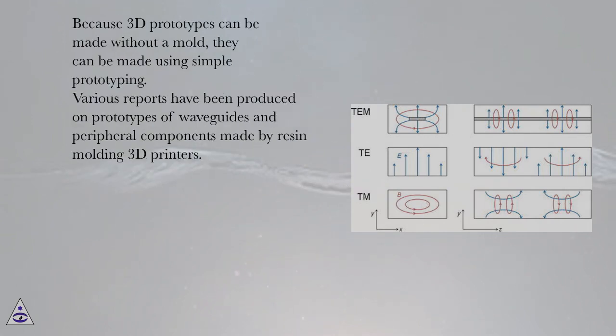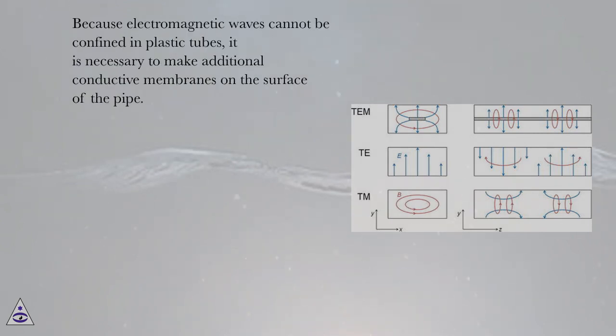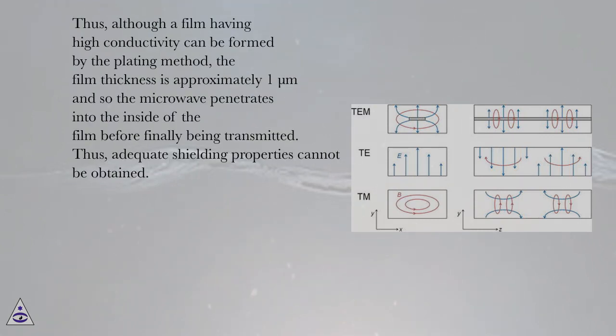Because 3D prototypes can be made without a mold, they can be made using simple prototyping. Various reports have been produced on prototypes of waveguides and peripheral components made by resin molding 3D printers. Because electromagnetic waves cannot be confined in plastic tubes, it is necessary to make additional conductive membranes on the surface of the pipe. Thus, although a film having high conductivity can be formed by the plating method, the film thickness is approximately 1 μm, and so the microwave penetrates into the inside of the film before finally being transmitted. Thus, adequate shielding properties cannot be obtained.